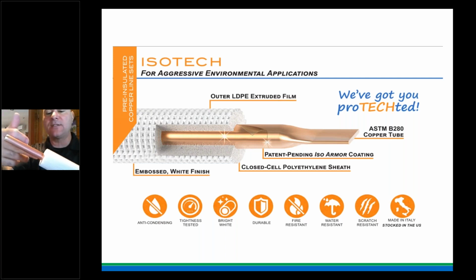So what happens is water gets inside of the jacket, right? Water will run inside the jacket. This insulation doesn't absorb the water. So the water will stay on the copper, and then the atmospheric VOCs will collect, mix with the water, create a little bit of acidity, and that's what eats away and causes the formicary corrosion. And for people that have never experienced it, basically what you'll have is little pinholes in the copper itself. It becomes acidic, and it will eat little pinholes into the copper. So that's what formicary corrosion is. We've come up with a solution for it, and we're real happy to have a solution.